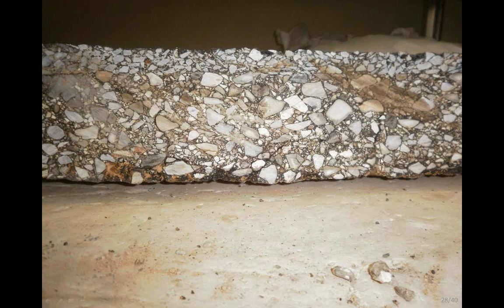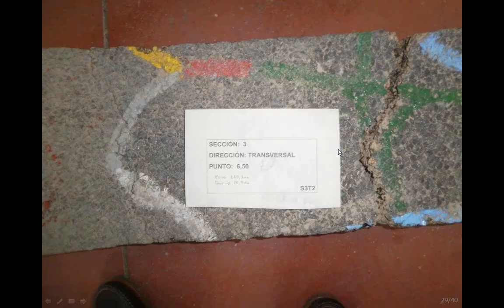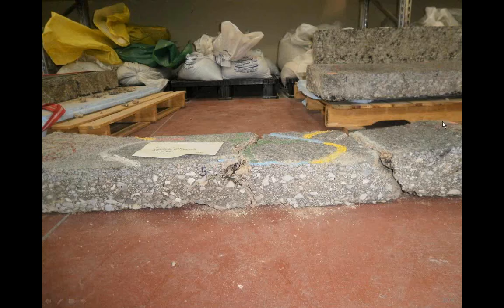And we are not sure whether this is reflective or bottom-up. Here you can see one of the slabs. This is the transverse direction, and vehicles would be moving along this direction. One interesting thing that you can see here is, okay, this is a transverse slab. In fact, you can see clearly the permanent deformation from the asphalt. You see the wearing course here is thicker than here.